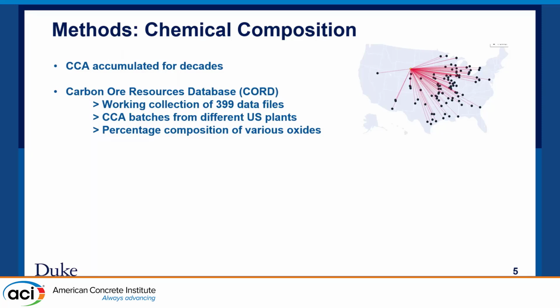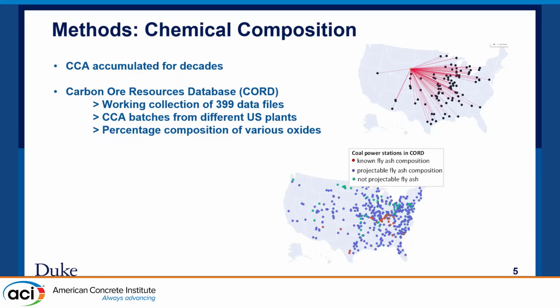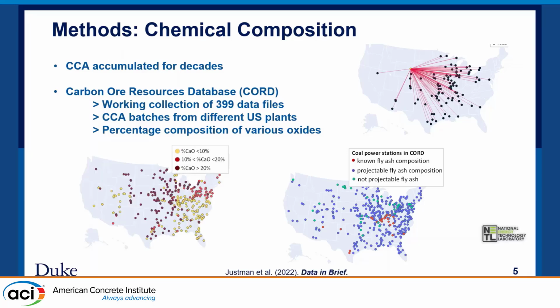This first picture explains the supply of coal for different coal-fired industries. This picture explains the coal power stations that have known fly ash composition, projectable fly ash composition, and non-projectable fly ash composition. And this picture explains the calcium oxide composition in those fly ashes. We have a limited amount of each batch of these coal combustion ashes, so there is an opportunity to see the mechanical performance of those coal combustion ash concretes and relate them to these oxide compositions.